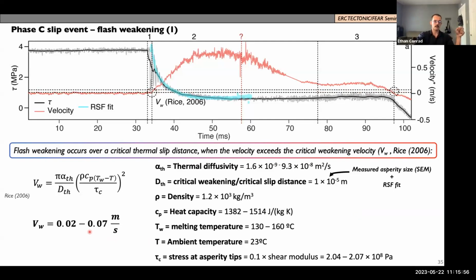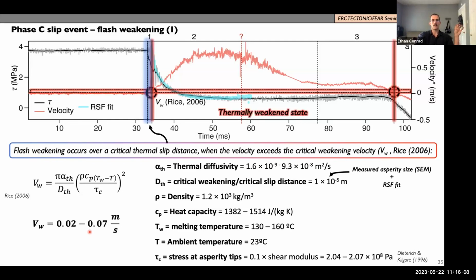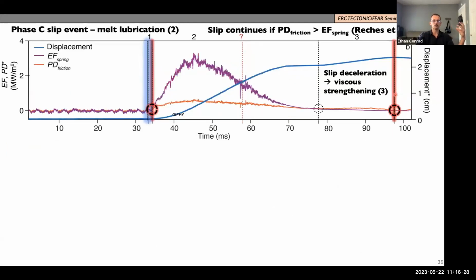So the slip velocity, the weakening velocity we get is around 0.02, 0.07 meters per second, and that's glowing here now red in these horizontal dashed lines. And so, as it's stated, flash weakening occurs over this critical thermal slip distance, and then the interface enters a weakened state when you exceed this critical slip velocity, up until you end the event and you start to cool and bond. So this is when you're in that thermally weakened state.